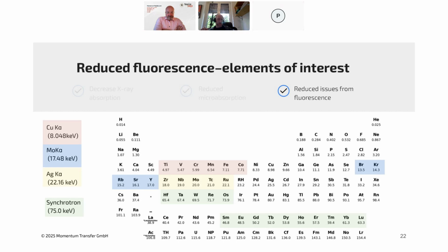But the good thing about this is, in addition to that, we have a very high flux of X-rays. And so one of the issues that you run into with getting worse quality data from these lab systems is that the fluorescence signal has its own noise associated with it, and that noise never gets better as you collect more statistics. So that reduces your overall signal to noise. But in our case, the flux is so high that you can still collect a good signal from the part of the sample that you care about.